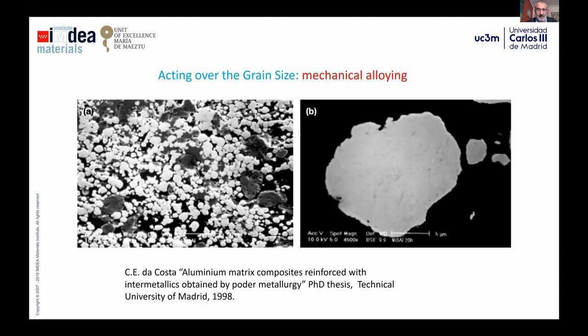One way, of course, is mechanical alloying. This processing is one way to produce powders in which you can get, as you see on the right, a mechanically alloyed intermetallic obtained by milling nickel and aluminium powders at high energy. At the end, you can get a microstructure in the powder in which you have a grain size much lower than any other possibility of processing.